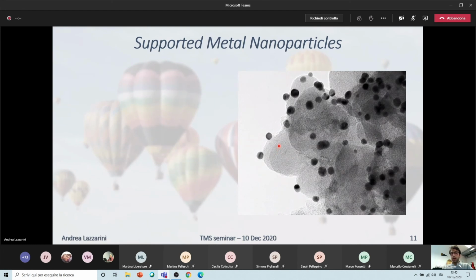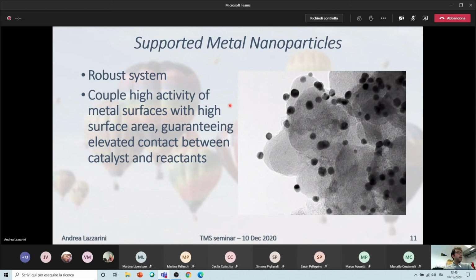silica. The idea of, again, supporting metal nanoparticles onto some kind of support is because, compared to the colloidal system in the liquid phase, you can have a more robust system, because in this way you kind of protect the nanoparticles from the coalescence phenomena, so the particles growing together, so you reduce the surface area of the catalyst until its deactivation. You can again couple the high activity of metal surfaces with the high surface area of the nanoparticles, and this way you can guarantee a higher contact between the active phase and the reactants.